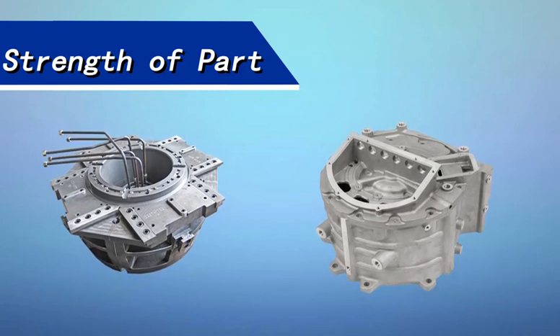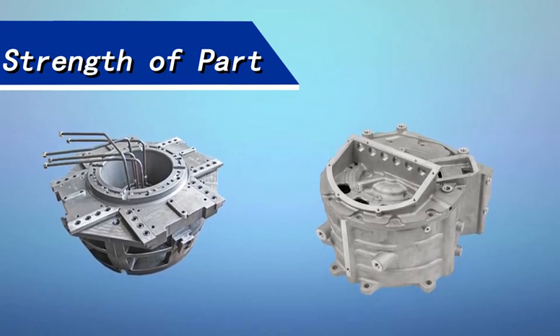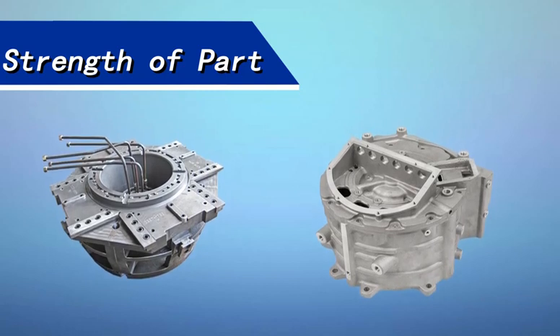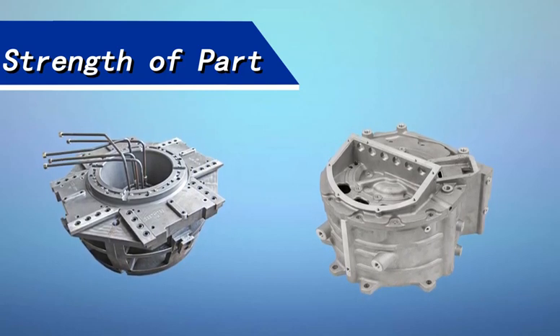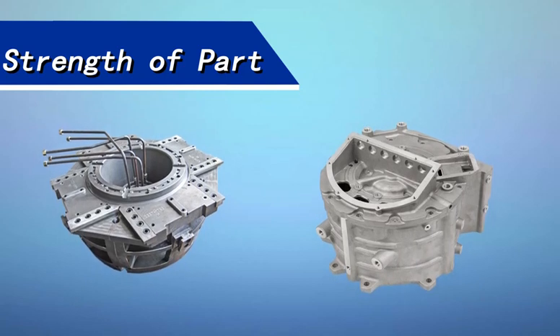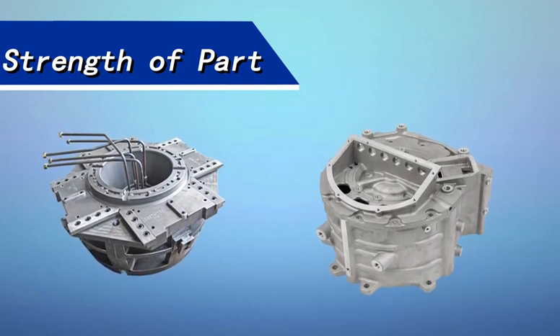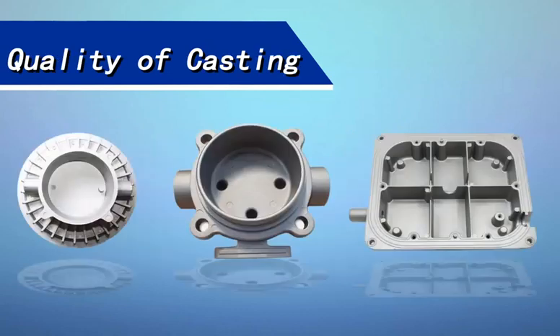Due to its better purity, low-pressure casting products' elongation is higher. High-pressure casting possesses better strength, but lower elongation. Elongation: how long the parts can be stretched before broken under pulling forces. Quality of casting. Low-pressure castings generally exhibit superior quality when compared to high-pressure castings. This is because the volume reduction resulting from shrinkage during solidification is offset by a continuous injection of molten metal into the die cavity until solidification is complete.